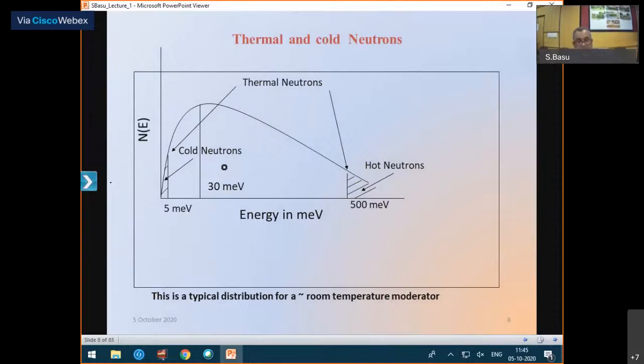Typically this is a Maxwellian distribution with a peak around 30 millielectron volts, and in this Maxwellian you have a portion which is typically, we say, neutron energy less than 5 millielectron volts, and that gives us a handle for using them for very, very slow dynamics. At the same time, we also have neutrons which are called hot neutrons. They can be used to understand structure at very short length scales or reasonably high energy excitations in solids.